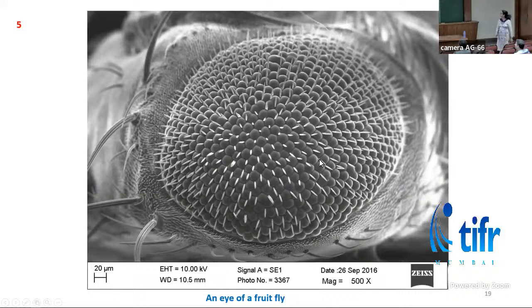This is an eye of a fruit fly. As I mentioned earlier, this sample goes into the high vacuum. So for biological samples, it is a little difficult to image them because they need to retain some moisture in the sample to be imaged. Otherwise, this sample will degrade if we put it into vacuum. But there are some fixation procedures used by biologists by which it creates a certain amount of moisture which is tolerable by the high vacuum, and then we can image these kinds of samples also.